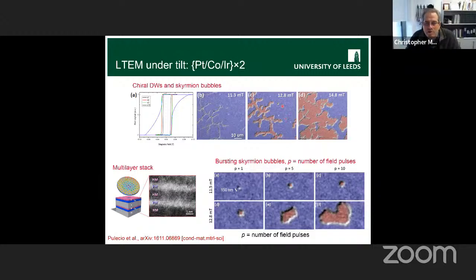So we get these fairly typical dendritic domain structures, but you can see here and there, like these little objects, there's one here, there's one here, maybe one here, that are little detached, discrete things. And if we zoom in on one of those, here's one. It's about 150 nanometers across, and that's a little skyrmion by itself in this multi-layer system.